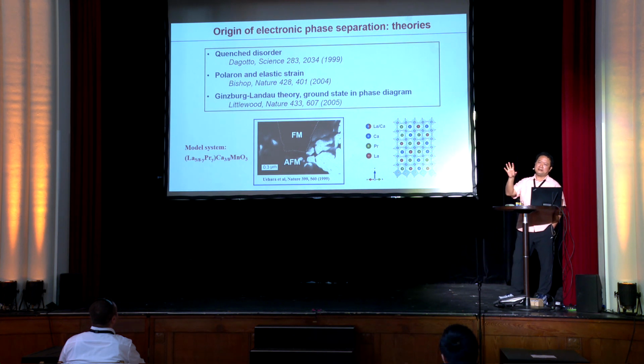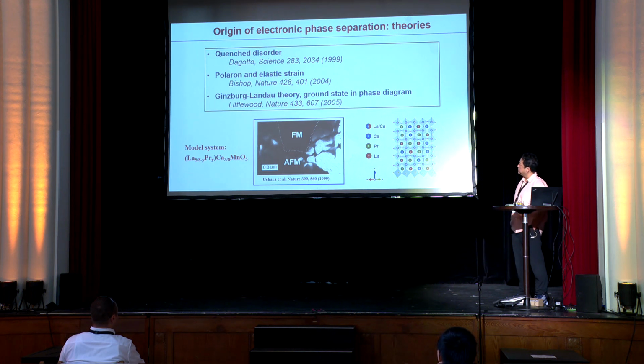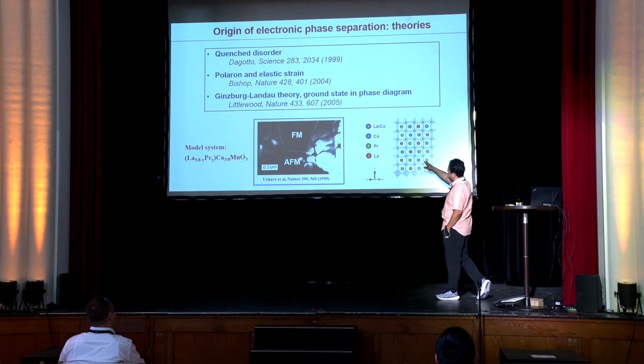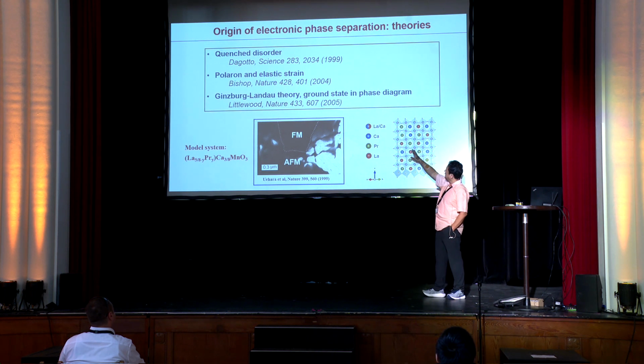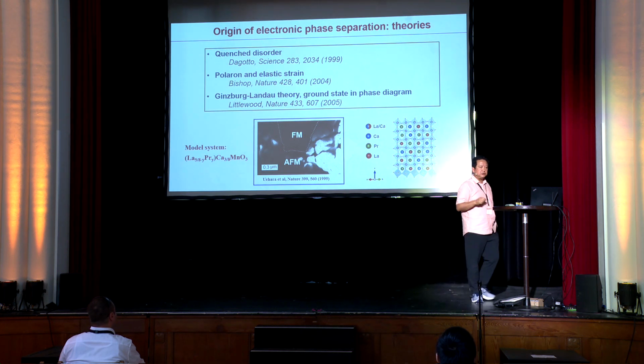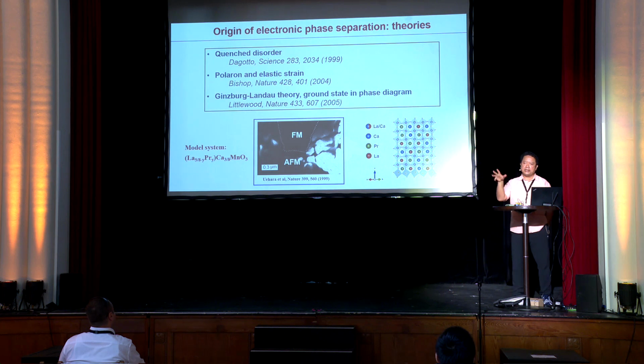So the model is probably correct from a theory point of view, but it's not necessarily catching exactly the sense about the experimental systems. But anyway, Elbio Dagotto, Alan Bishop, Peter Littlewood, and many other theorists have reported their theories explaining the physical origin of the systems. And they all like to use one of these model systems, lanthanum praseodymium calcium manganese O3. In fact, it is just an ABO3 perovskite, but on the A site, the lanthanum, calcium, and praseodymium ions are mixed together. So they are sort of randomly occupying these A sites. That's how the crystal structure is.